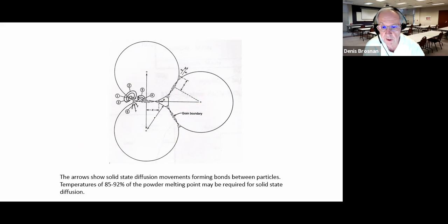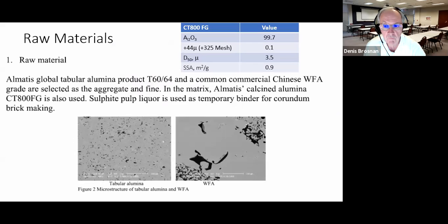Of course, any diffusion control reaction means we have to get up to sufficient temperatures to cause atom movement to take place. And usually that's a fairly substantial percentage of the melting point temperature. Now, the raw materials used by these guys were tab alumina, and they also were comparing some mixes to Chinese white fused alumina grades. They were trying to look at compositions that had the best slag corrosion resistance.